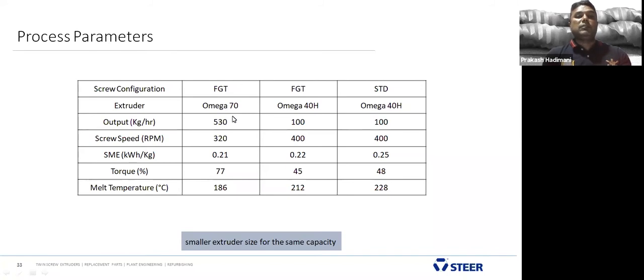But in the 70 millimeter extruder, we could achieve 530 kg per hour. For FGT in the Omega and for standard, we maintained the same output, 100 kilo. The RPM is constant. But if you look at FGT and standard, the specific mechanical energy, the power consumption, is higher in standard technology compared to FGT. And also melt temperature: there is a 40-degree variation between our 70 millimeter FGT technology and the standard. FGT 70 is giving 186 degrees centigrade, but the standard technology is giving 228. That means a 40-degree higher melt temperature in standard technology.